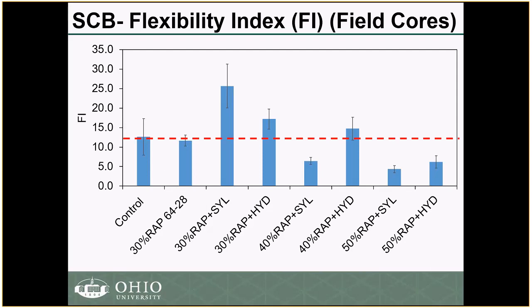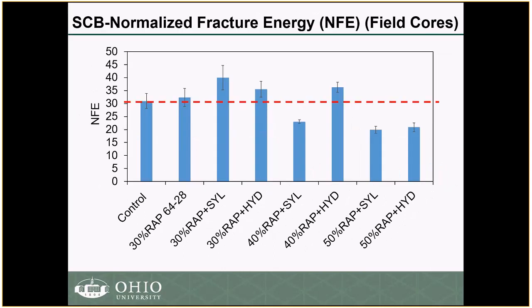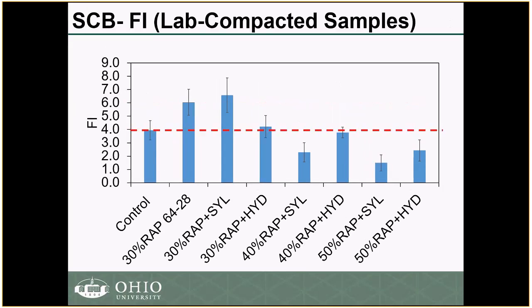With the 50% RAP, and this is where we have about 0.53 RBR, both did not really show an improvement. They had a significantly lower flexibility index as compared to the control mix. For the NFE, it's a very similar trend to what we have seen with the flexibility index. Both parameters are giving similar results. The only difference is the variability between them.